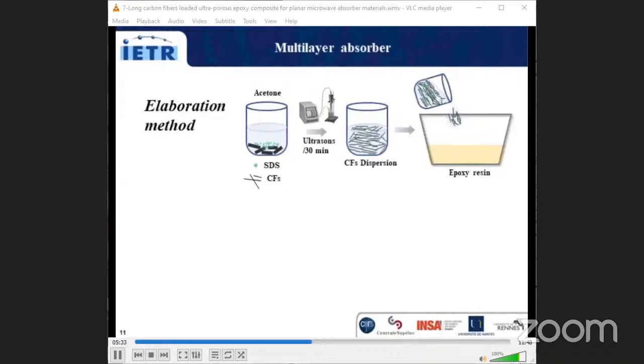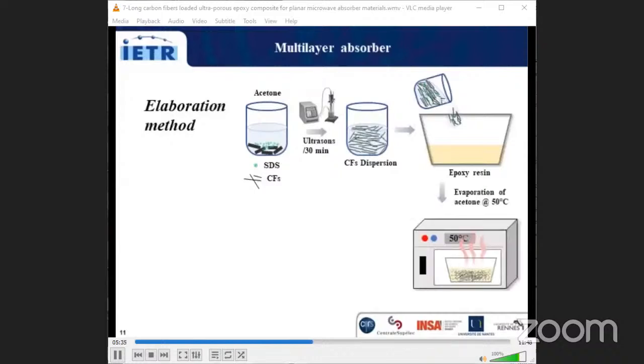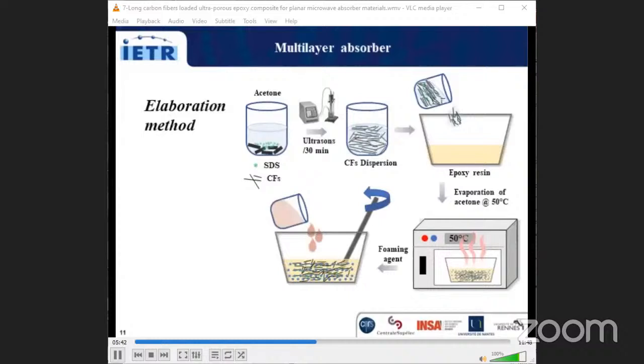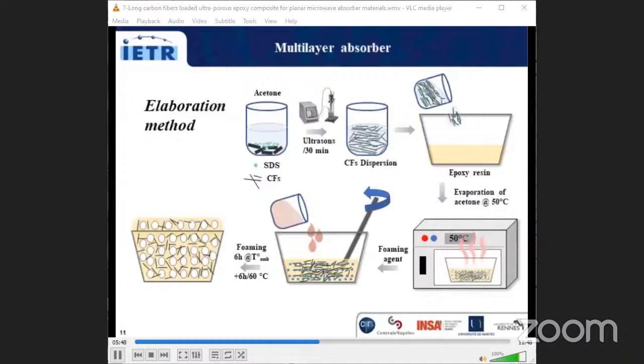The whole mixture is put in the oven to evaporate the excess acetone and to leave only the desired amount of acetone in the mixture. Then the foaming agent is added and mixed with the spatula, and this mixture is left at room temperature for 6 hours to finalize the foaming steps, then at 60 degrees to finalize the polymerization. Finally, the foam will be cut to be characterized.